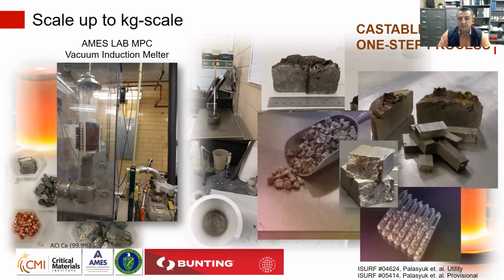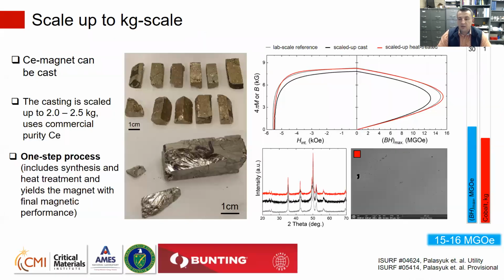And this is how the permanent magnet looks. And this is how it performs. And in fact, it outperforms the lab scale reference. And the indicator to the right already is not that negative after all. So we reached 15 to 16 megagauss-oersted, and we are using less and less cobalt.